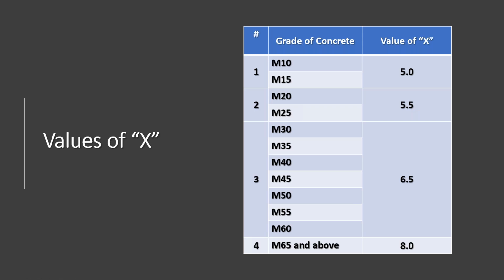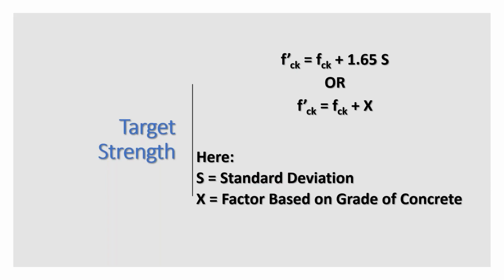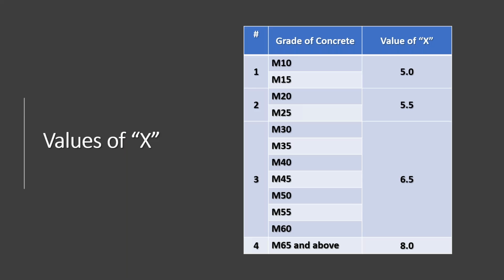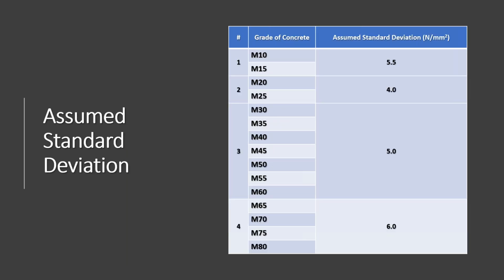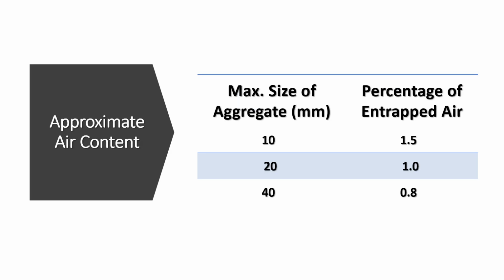So this is the table for the X value, the factor based on the grade, that you can add, for different grades of concrete, and this is the assumed standard deviation as per the new code. And this is the percentage of entrapped air for different sizes. For 10 mm it is 1.5% by volume, for 20 mm 1%, and for 40 mm 0.8%.